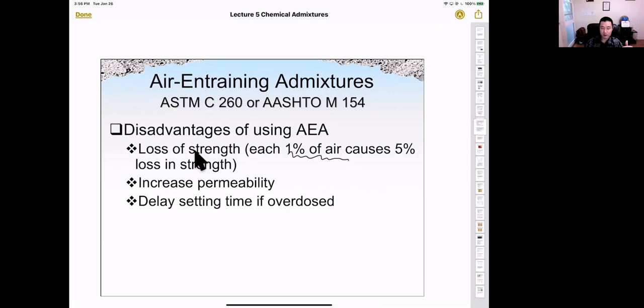It will also increase permeability, which means water and harmful chemicals such as chloride, the seawater, can penetrate the concrete and do the damage more easily. So that's not good. Sometimes air entraining agent can also delay the setting time if overdosed. Okay, change the setting time of concrete.